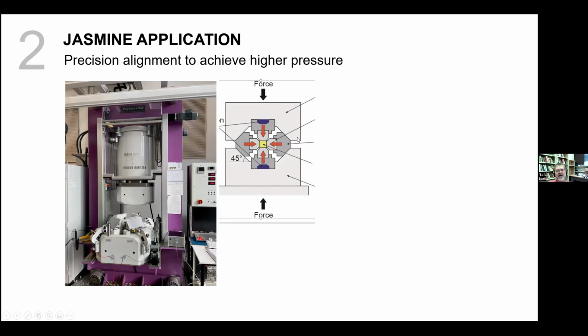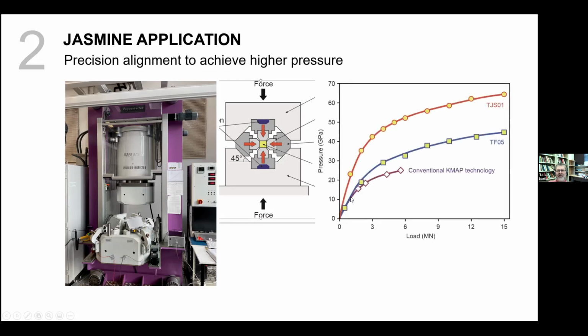And it turns out that the side forces are not quite the same as the top and bottom forces because of the sliding geometry and the flexure of these big blocks on the outside. This cube is basically your carbide cubes or sinter diamond cubes. So what Katsura did, which is quite clever, is hollowed out the top and bottom to make them softer. So there's actually an opening inside there. And by doing that, he could use more brittle carbide without breaking it as much.